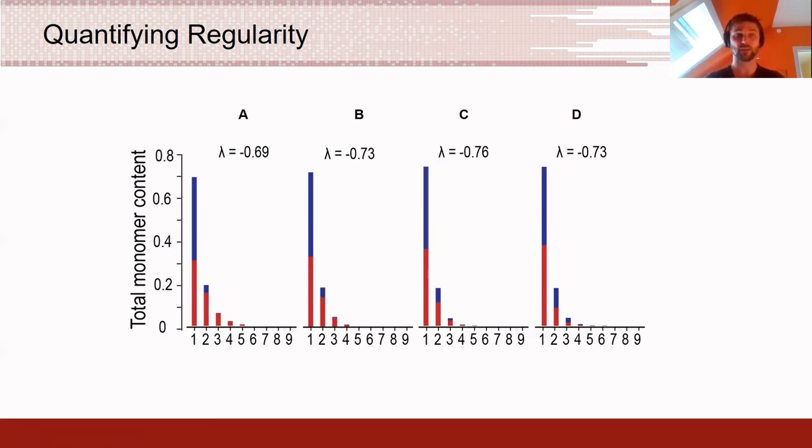And we could see that with the conditions run, including the conversions, the most alternating copolymer we had was polymer C. So the way this chemical correlation function is to be read is that a value of -1 is perfectly alternating, a value of 0 is perfectly random, and a value of 1 is a perfect block copolymer with equal lengths of each of the blocks. So for this particular system, I would assume that the closer we can get to -1, the better.